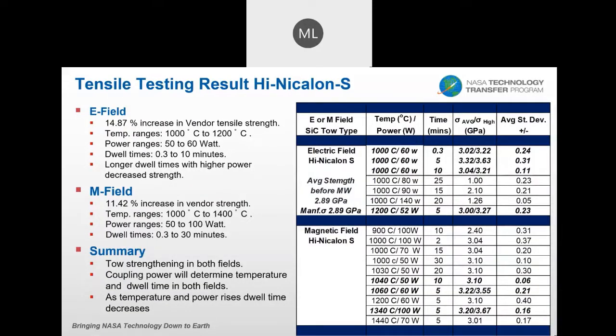So now the testing results for the Hi-Nicalon-S. And in this case, the fiber, as you recall, had the same strength as the vendor reported fiber. So what we saw here was about a 15% increase in the vendor tensile strength. Temperature ranges from 1000 to 1200 degrees. Power ranges from 50 to 60 watts. Dwell times from 0.3 to 10 minutes. Longer dwell times with higher power decrease the strength.